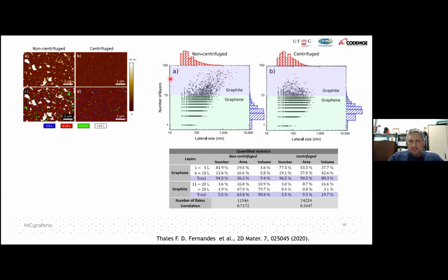They have a lot of layers, so this is graphite. They have something like 50 layers or more, and they have a size of around 1 micron. And then the centrifugation just cuts this here, okay? But if you look at the statistics of numbers, it doesn't change much. It means if somebody has this graphene and shows you the histogram for lateral size or number of layers, it looks very much the same as if you have this graphene here.